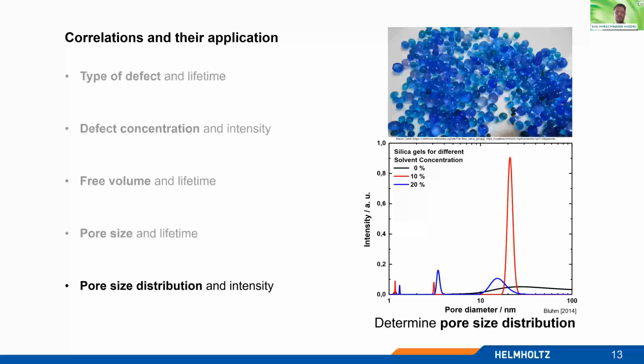Here, for example, we have a silica gel investigated with different solvent concentrations. And as you see, if you choose, like, 10% solvent concentration, you can manipulate the pore size distribution, as long as you wish for a high peak or broad distribution. This depends on the application you would like to see.